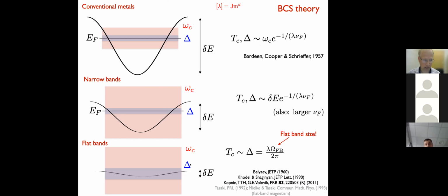Okay, and then there is the extreme limit of flat bands where the bandwidth is small compared to even the size of the superconducting order parameter. It's of course a self-consistent condition that you have to check. In this case, the delta is actually linearly proportional to this interaction strength.